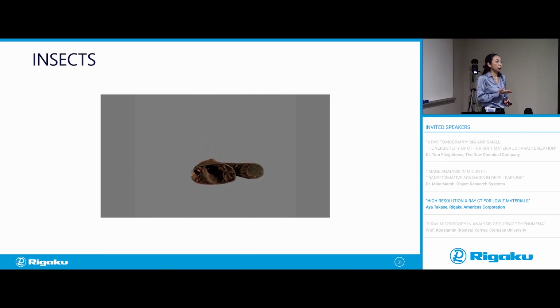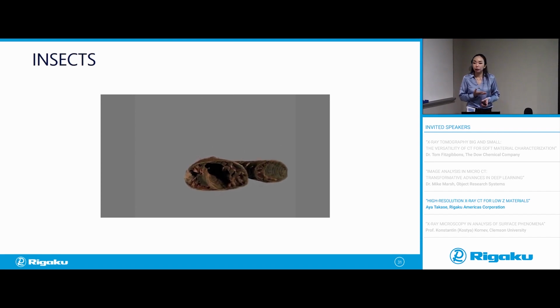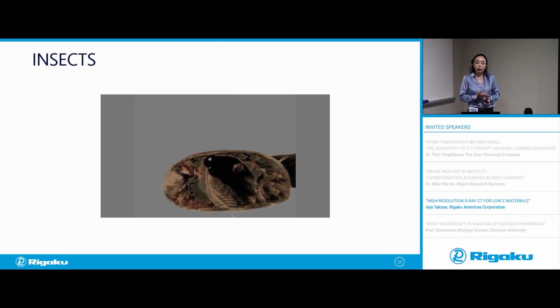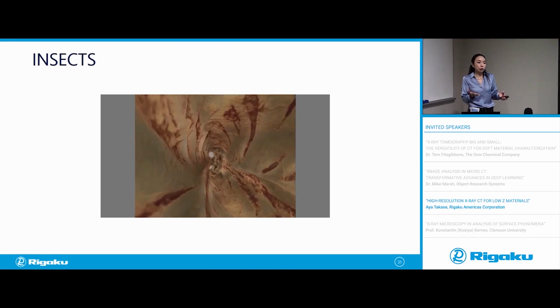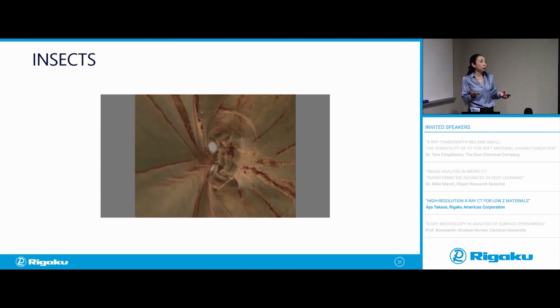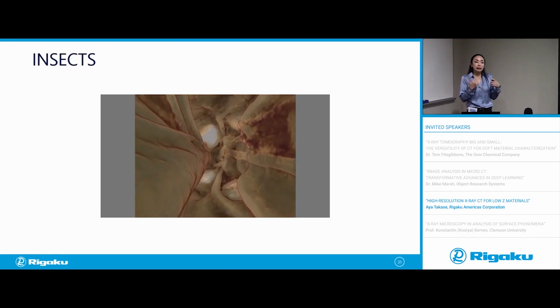And with this resolution, you can see individual hairs on the leg, and that you can do with SEM as well. But with X-rays, you can go inside of the leg and see all the details inside of the leg, or any organs of an insect, for example, without destroying the sample. And that's probably the biggest advantage the X-ray CT technique has. It's a 3-dimensional imaging technique, and it's non-destructive.